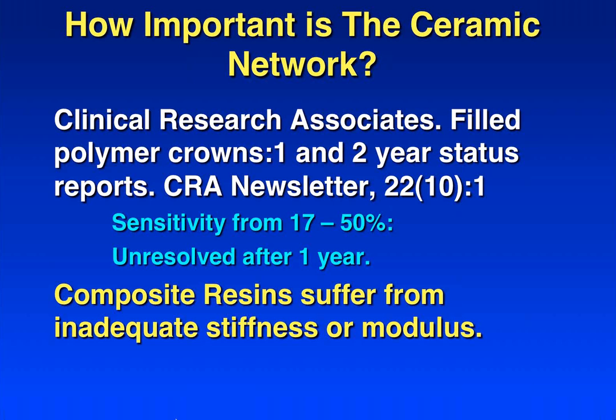They tend to flex under the stresses in the mouth, and they tend to pump fluids in and out of the dentin, which causes sensitivity. The other problem that happens is they tend to flex enough so that you may get the bonding of that restoration off of the underlying structure. So you have lots of stresses as this restoration starts to flex. As you're chewing on it, fluids go in and out of the dentin. That creates lots of pain. And you also start to open up the margins and the bonding layer in between the composite resin crown and the actual cement. Often it comes off clean. The cement doesn't adhere to the composite resin crown, and it'll pop off as these stresses occur on the material.